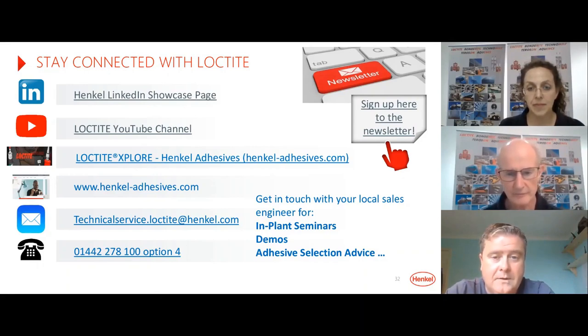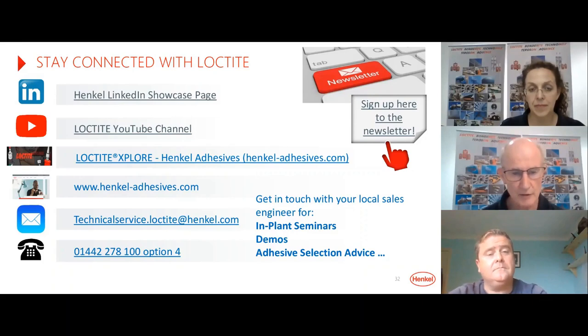Thank you very much. Second question: do you have any adhesives that are recommended where you have a severe peel load? Yes, so some of the rubber toughened epoxies are suitable for peel loads. What happens is when you've got a standard epoxy or a product, they can be quite brittle. And so as soon as you generate a stress at one end of the joint, a crack is formed, and that crack can propagate through the adhesive.